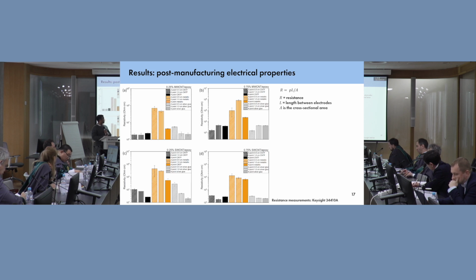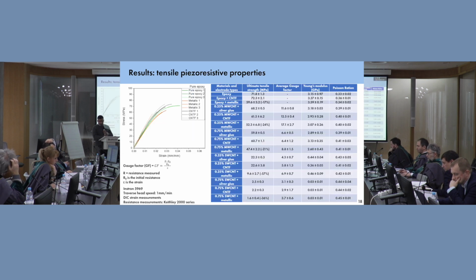And our standard that we used for this was a conductive silver glue, which is used in multifunctional nanocomposites everywhere for contact creation. So our performance here is very, very similar to standards which are used right now. Silver glue or paste has the issue that with manufacturing, it's going to up your costs and it's not reusable. But in our case, with the carbon nanotube fibers, we do see these properties there.